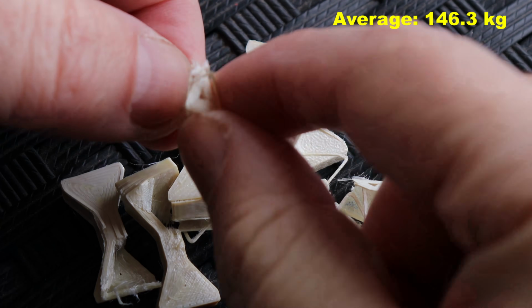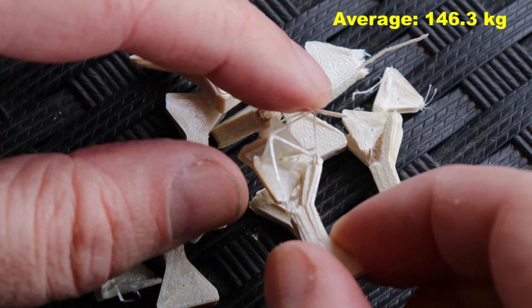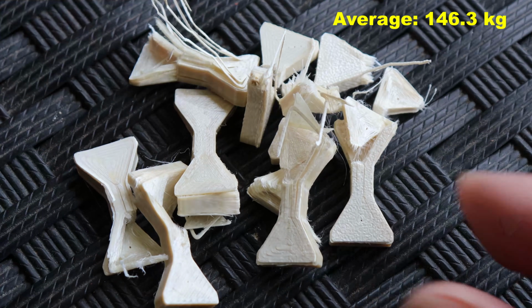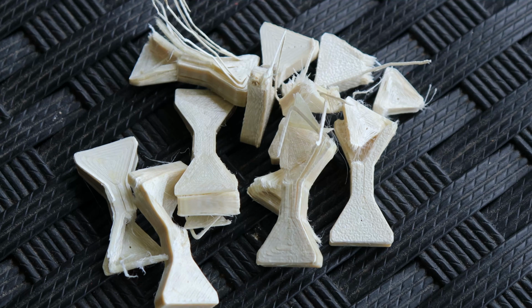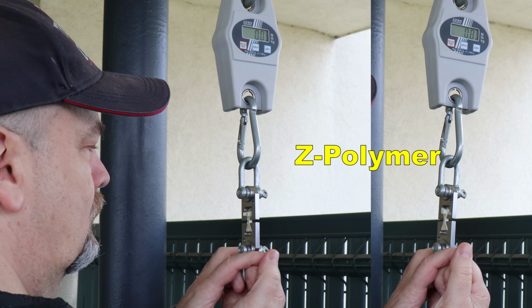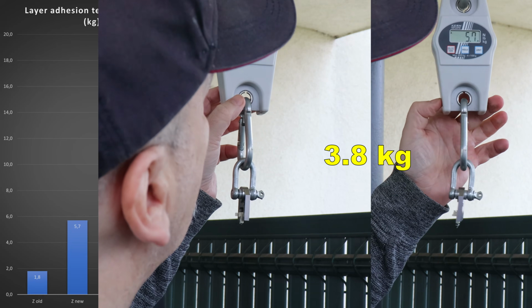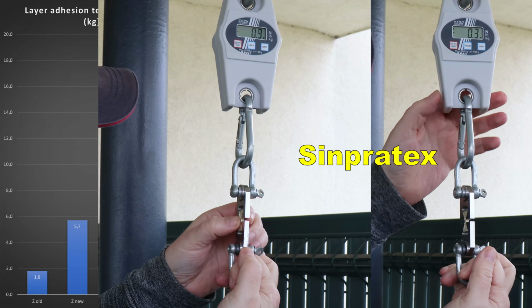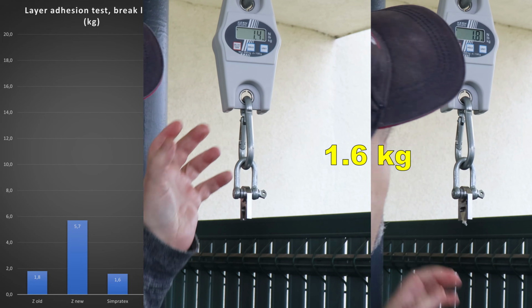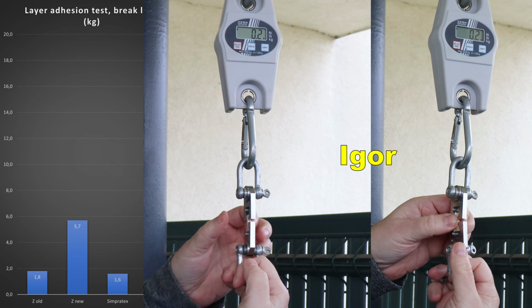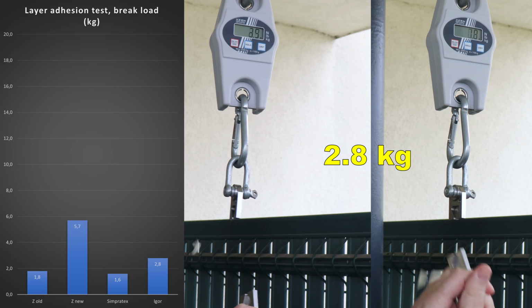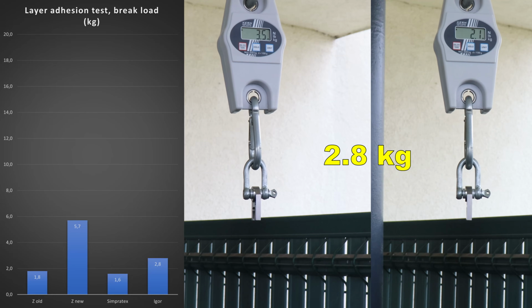Very strange failure. Instead of the break at the smallest cross-section area, it has some delamination and it slipped out from the holders. And now the layer adhesion test with vertically printed test objects. The big average is 3 kilograms, which is below acceptable. And why is this important even for those objects which will be loaded in X and Y direction only? I explain in the conclusions part.